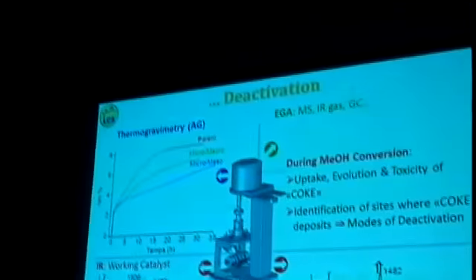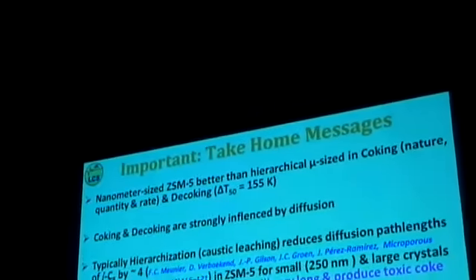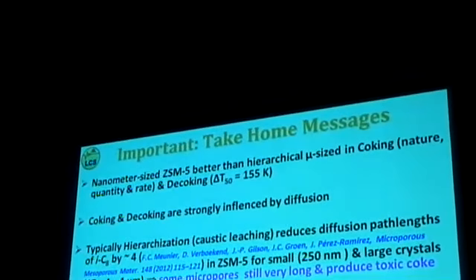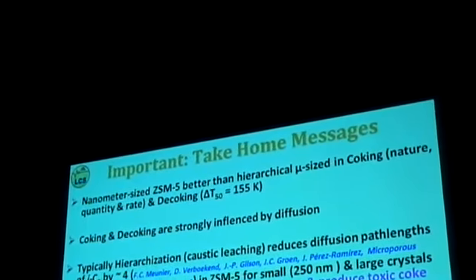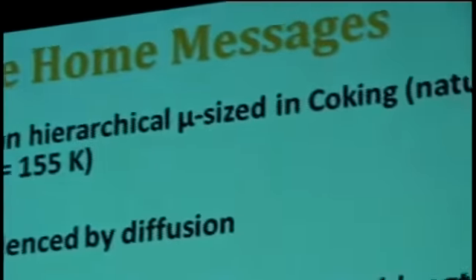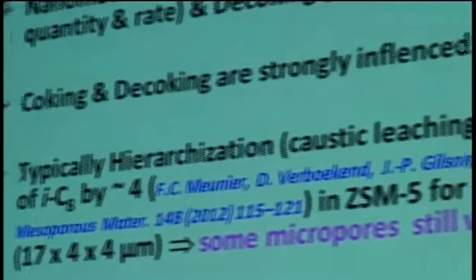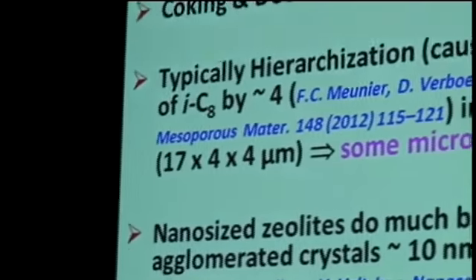So I will just go to the conclusion. What I think are the important take-home messages. So far, nanometer-sized ZSM-5 is better than hierarchical, and by hierarchical I mean materials that have been produced by post-synthesis modification. The reason is that the level of defects is much lower.